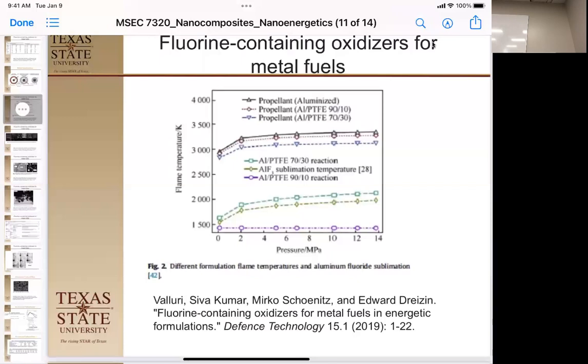oxidizer. When we move down there, we see we get the same flame temperature on it, no matter how much pressure is inserted here. So in that case, what that means is that as the pressure goes up, you still are burning hot, which means that you can use it as propellant because you can still have thrust. Even as you are getting back pressure inside your thrust nozzle, you can still have it burn. Now, if we look at that right here, we also see that the byproduct from this is aluminum trifluoride, which is a gas. Well, in this case right here, it's subliming at this low temperature under these different pressures here.